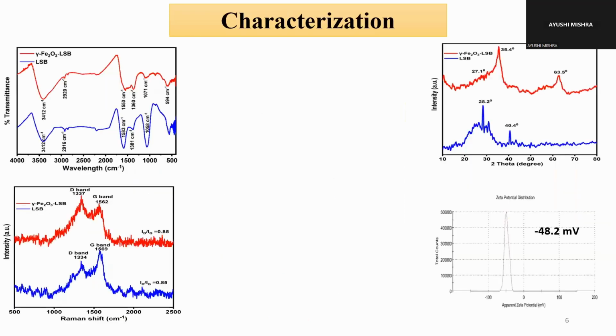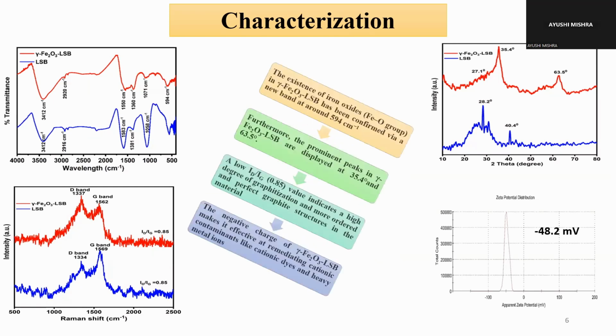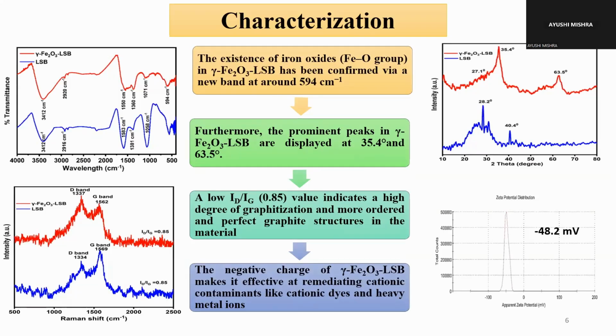This is a synthesis scheme, and these are the characterizations I've done for my biochar. That is Lagenaria siceraria biochar, LSB, and the magnetite functionalized biochar is LSB magnetized. These are the FTIR, XRD, Raman, and zeta potential spectra of my material. As we can see, functional groups like OH, CH2, carbonyl, and carboxyl are present on the surface. Also, there's an Fe-O group, which is confirmed by a new band at 594 cm⁻¹.